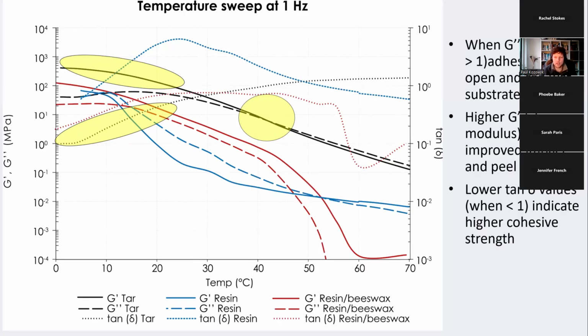To give a bit of a practical idea, to put that into perspective, some modern general purpose hot melt adhesives generally have a storage modulus, at 25 degrees, of between 50 and 500 megapascals. The birch bark tar here is about 150 megapascals, so it's within that range. And they usually have a tan delta value at the same temperature of about 0.1 to 0.3. With the birch bark tar at a little bit cooler, it's got a tan delta value of about 0.3. So it's close. It's approaching the quality of some general purpose hot melt adhesives that we use today.